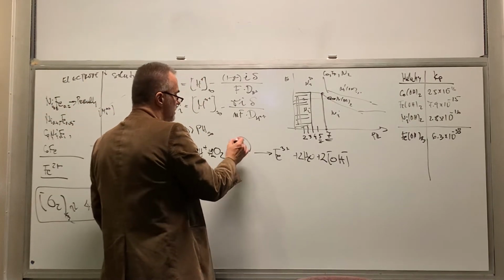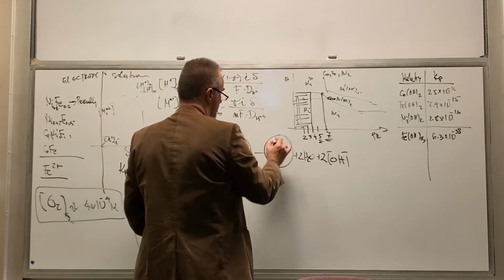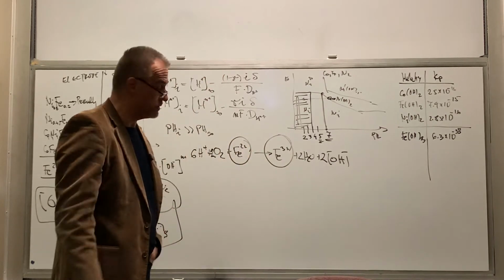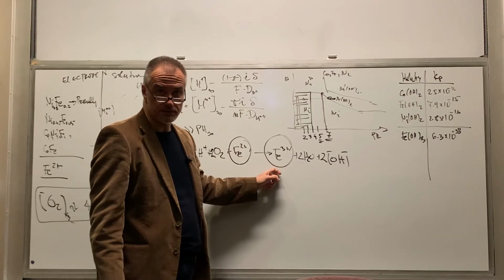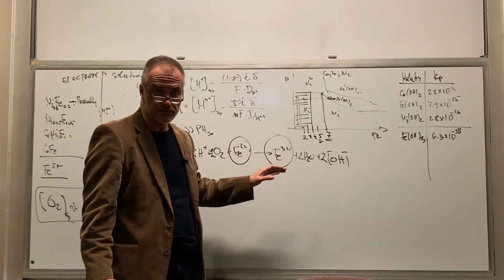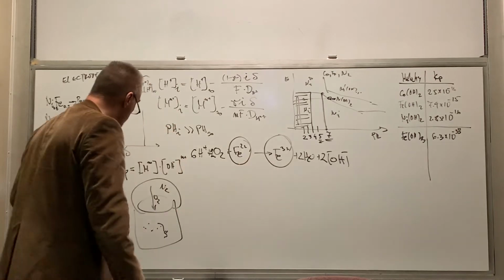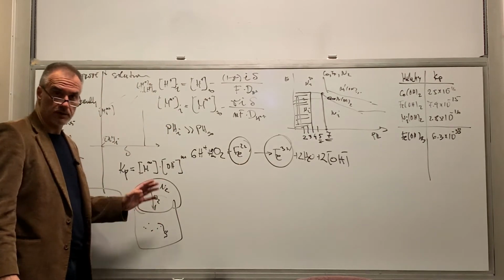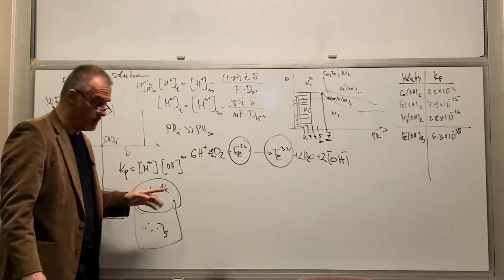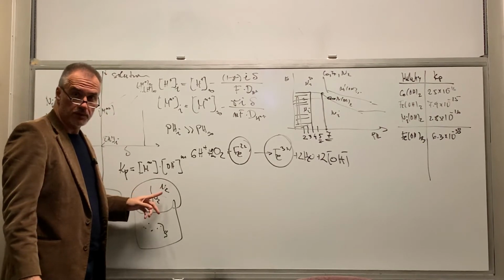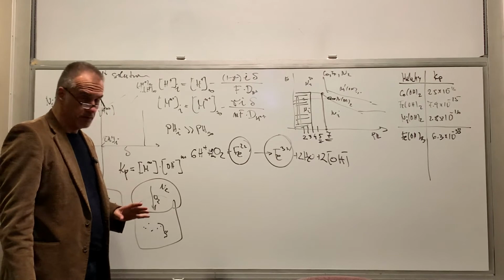So the really important thing is that oxygen dissolved in the solution oxidizes iron 2 plus to iron 3 plus. That's the process that happens no matter what you do, unless you put in some nitrogen trapping and deaeration, etc., etc. That's one problem. So let's say you solve this by putting nitrogen trapping here, right? You have another problem.